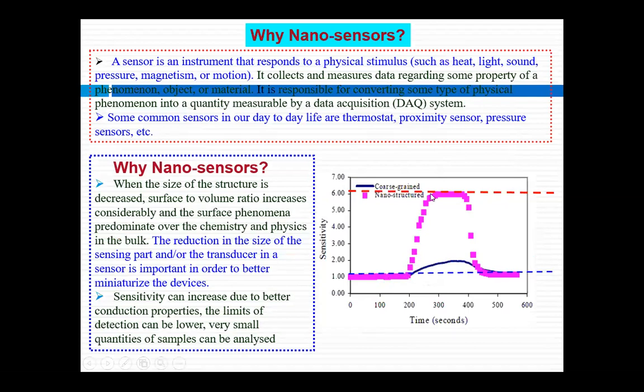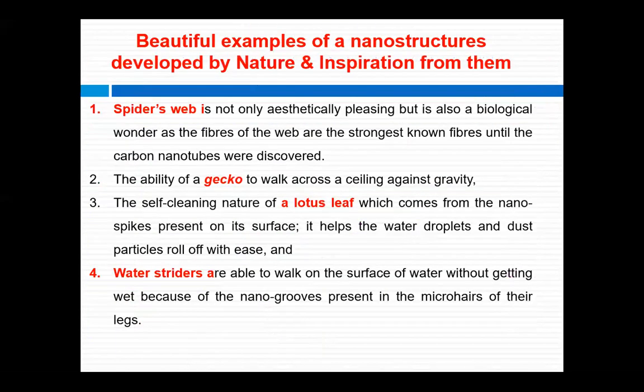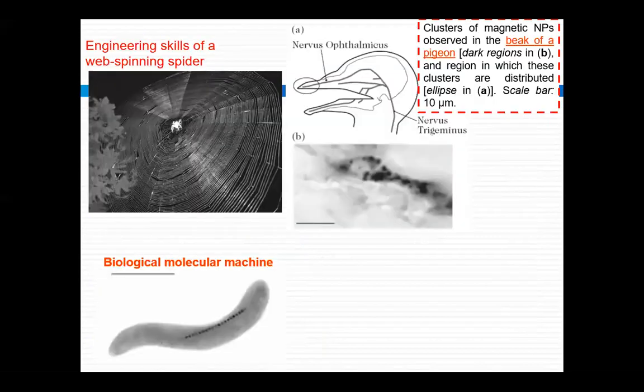You can see that this reddish line around 6 units, and the bottom solid blue line, indicates the sensitivity of the conventional sensor. So compared to the conventional sensor, after constant time, you can see how the nanosensors are better than the conventional. The sensitivity is more than 3 times better. Again, it is because of the higher surface area to volume ratio. Because more atoms are on the surface, each and every atom can play the role of reacting with the outer species. So there will be a change in the resistance, and that signal will be okay. Next, this I already discussed.